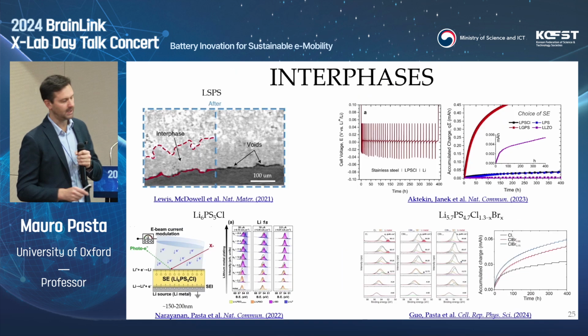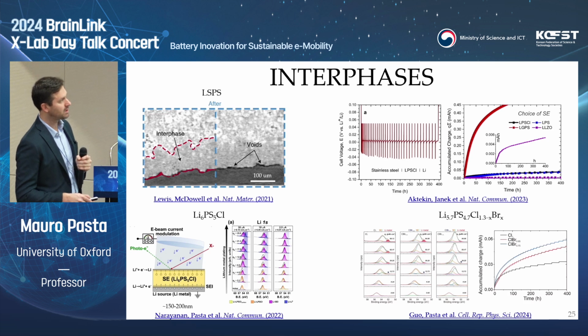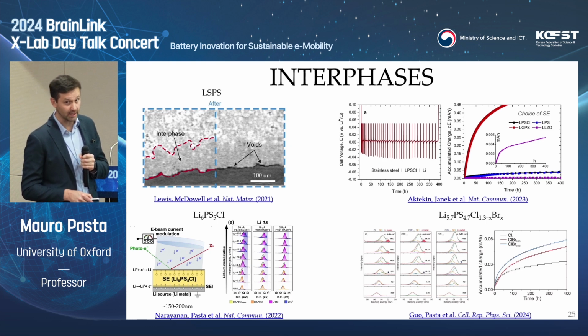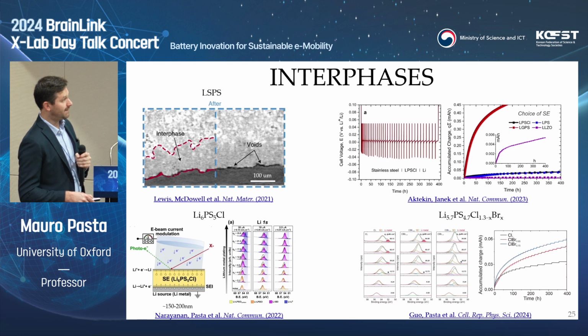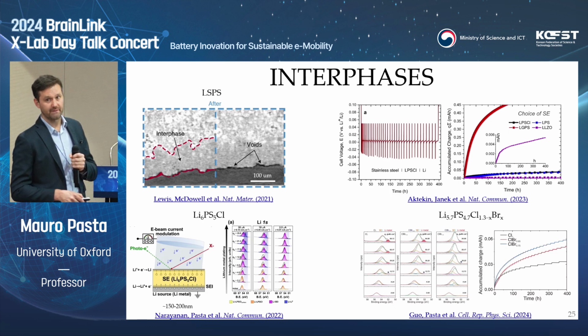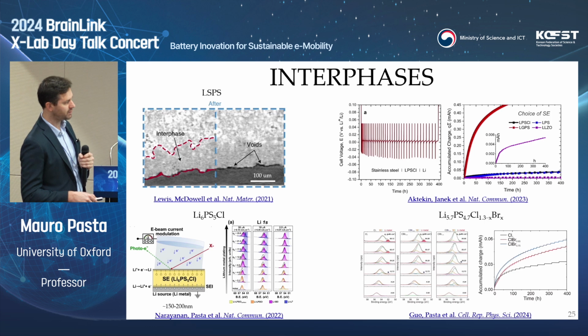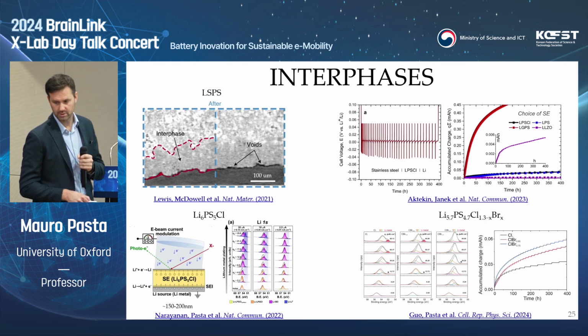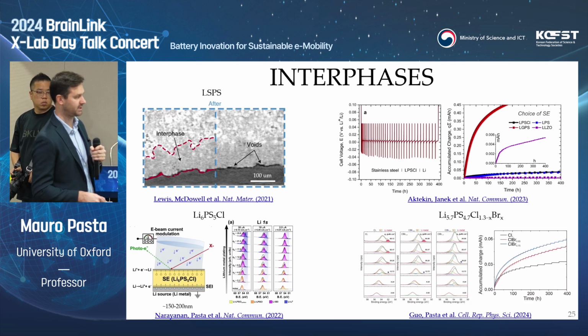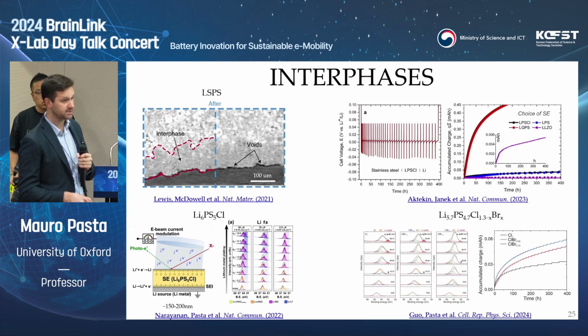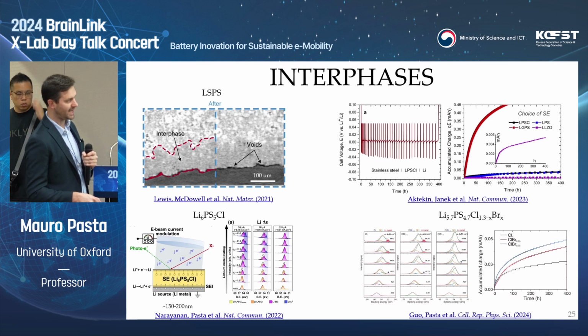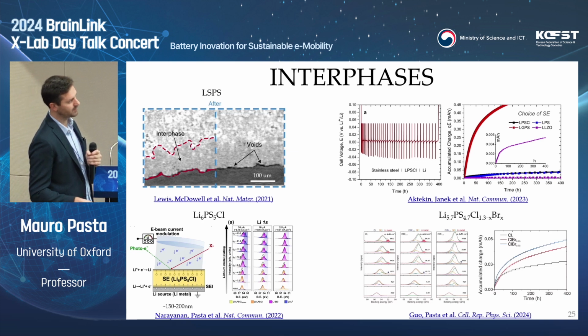One final slide, and then I will wrap up. Interfaces. Another thing that has been less characterized is what is actually happening at the interface between metallic lithium and a sulfide solid electrolyte in particular. Turns out that this interface is quite reactive. People used to think, in particular in the presence of an argyrodite, that this interface would be self-passivating, so you would form some sort of an SEI, but the SEI would not propagate over time. We now have evidence this is actually not the case, and this interface keeps growing over time, so understanding it will be critical, and I will give a talk in a couple of days specifically on that and our understanding around interfaces.